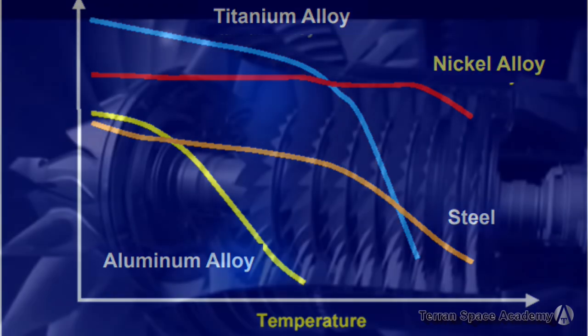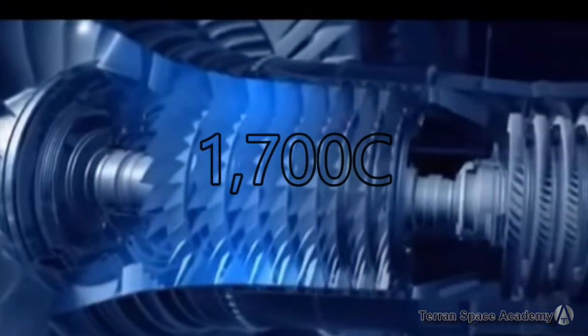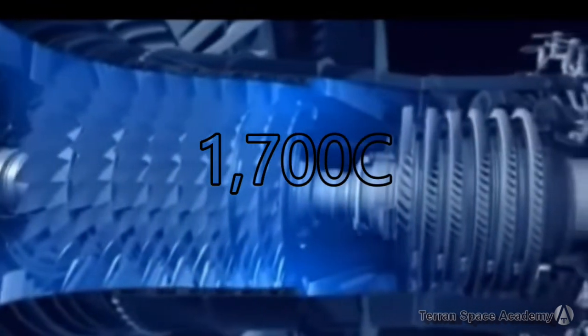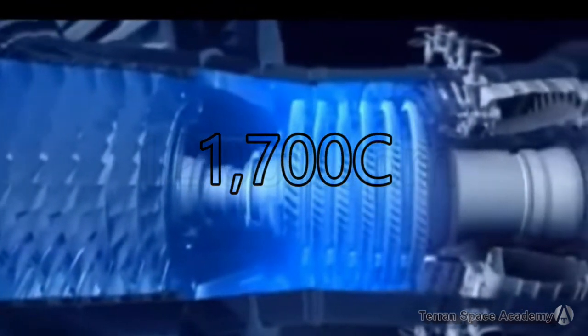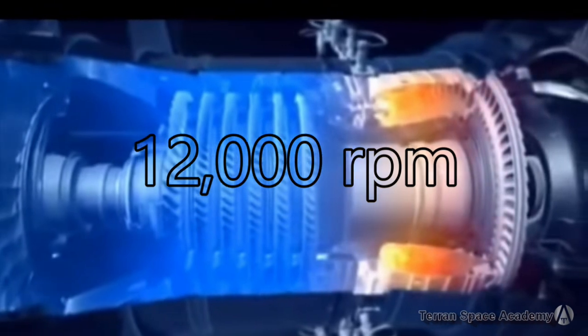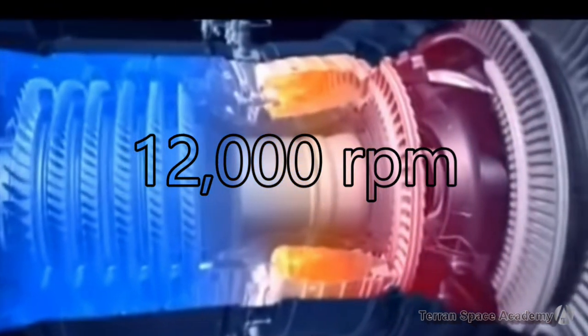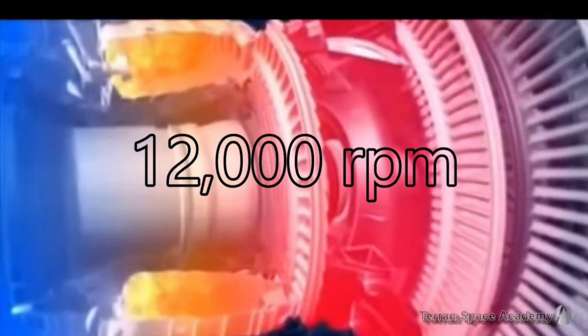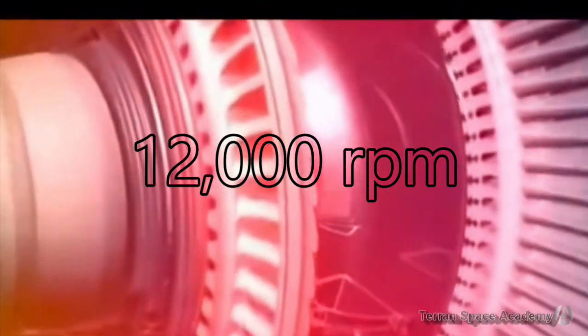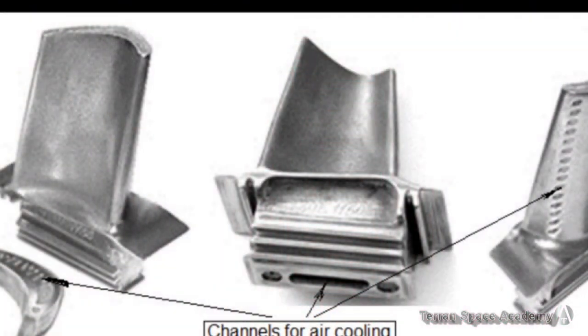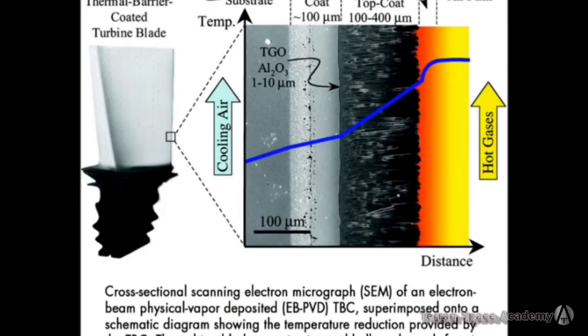The gases from the combustion chamber of a jet engine are at 1,700 centigrade, and the high-pressure shaft spins at up to 12,000 RPM. To keep even Inconel from melting, the blades are cooled by coating them with a low-heat conductive ceramic and have internal channels through which cooler air is routed, much as fuel is circulated around the nozzle and combustion chamber of a modern rocket engine to prevent overheating.